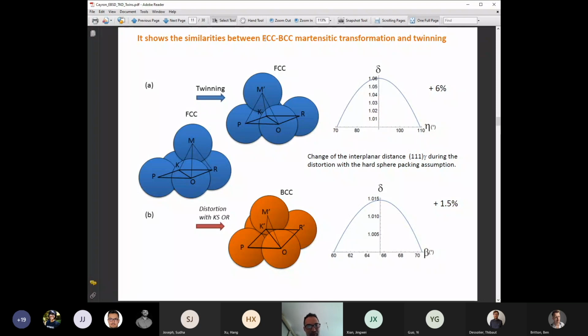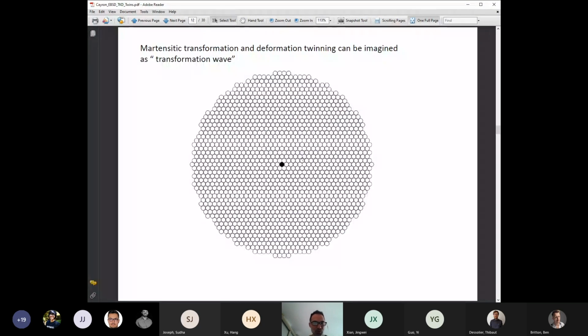And here, what was represented was a movie. I think it was important, but it was a movie to explain how I could transform as a wave. The idea was to show that deformation twinning or martensite, it's better to represent that as a wave of transformation. So here I had a movie, but I will not show you. Here is the result of the movie. You start imagining that at the beginning you had a hexagonal stacking, and in the middle you have a cubic stacking. And you can change continuously.